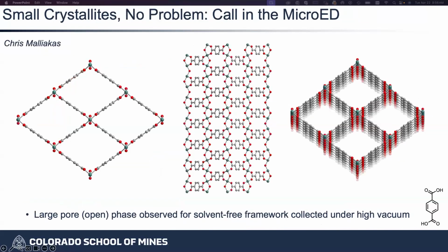And so what we've been doing is leveraging micro-ED. The reason micro-ED has been so critical to this is because these are aluminum oxo-coordination, very strong bond coordination interactions. And if you've ever worked with metal organic frameworks before, you know that the stronger the interactions, probably the smaller the crystallites you're going to get. And so these are very fine powders, garbage for single crystal, perfect for micro-ED.